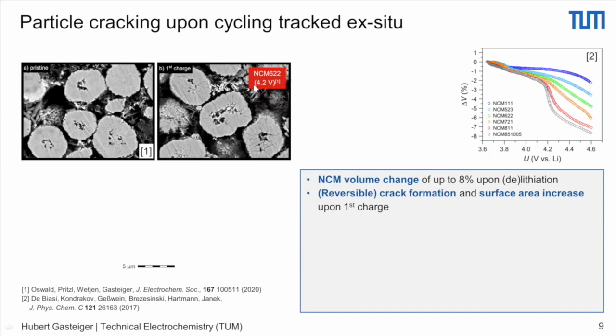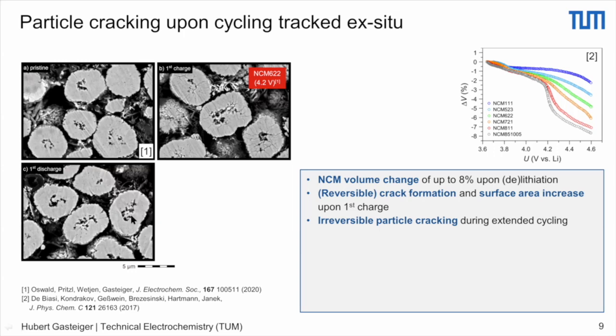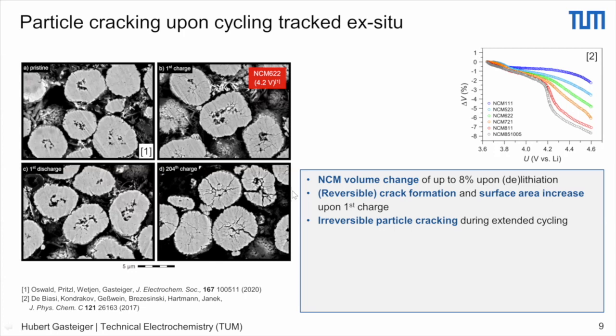So when we cycle the material, in this case to 4.2 volts, what we can see after the first charge in the FIB-SEM is that you can now see the development of cracks in the material. These cracks actually close again after the first few cycles when you go into the discharge state. This can be shown here. You can see that it closes a little bit again. Of course, very qualitative in this case. And when we cycle for many cycles, then of course, even in the discharge state, you see the cracking of the material quite clearly. So the cracking is actually irreversible.